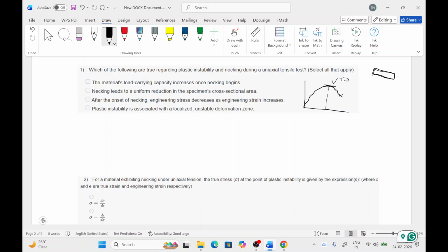But after this point, UTS, the deformation gets localized at some region, and necking of the material starts. So the deformation gets localized at some region, and the further deformation will happen in this region because the local stress at this point is higher, so only this area will get deformed and lead to fracture of the material.